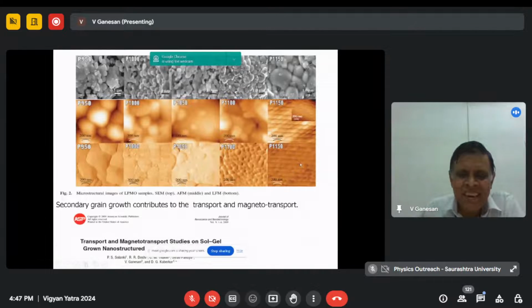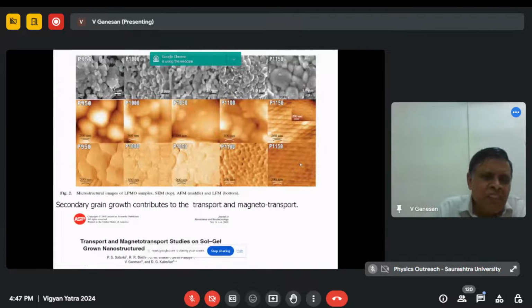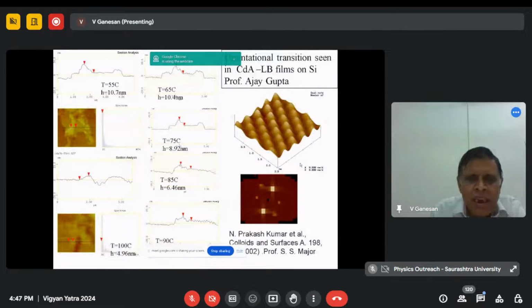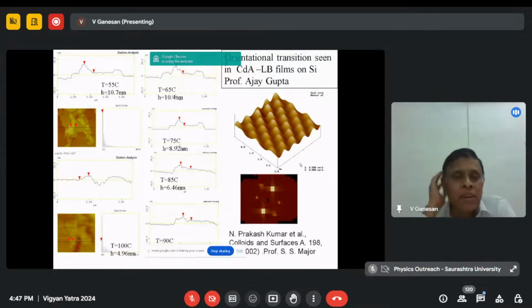It is like interference contrast in the optical microscope. It will not show you anything within the grain, but when you go from one grain to another grain, there's a discontinuity, and you will see a very high phase shift. So that is done. A lot of good papers came out in those days. I had good work on that, along with Saurashtra University as well. And then some good work again with IIT Mumbai, Professor Major and Gupta.